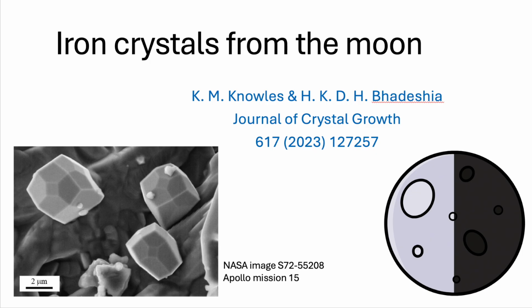But the surface, the very outer layer where growth is actually happening atom by atom, that must have been interacting with trace amounts of other elements or compounds, what we call absorbents, present in that lunar vapor. So the bulk is pure, but the surface chemistry during growth was complex. How does that surface chemistry end up dictating the final shape?